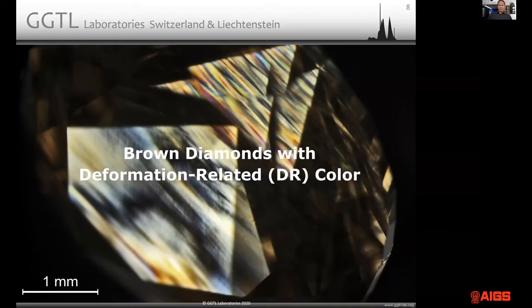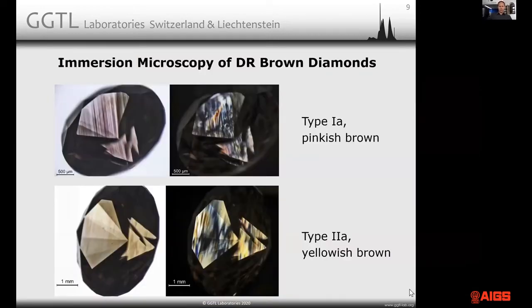Let's go straight into it, and let's start out with brown diamonds with deformation-related colors. I abbreviate those as DR, because otherwise you write out deformation-related all the time. Deformation-related diamonds are the ones that react positively to HPHT treatment. Here, the first slide shows you such diamonds in immersion on the left and in immersion with cross-polarizing filters in the exact same position on the right. These are the two most typical ones. There's type 1A diamonds and there's type 2A diamonds. Type 1A nitrogen-containing, and type 2A virtually nitrogen-free, at least via infrared spectroscopy.